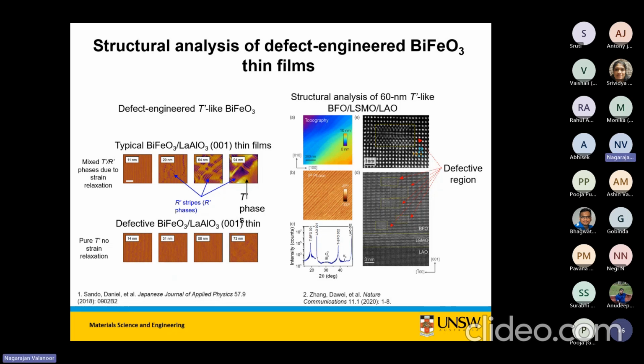So this X-ray is not very, very impressive, but if you look at those papers, you will find very nice satellite reflections, and the T phase is a really clean and beautiful interface and rocking curve and things like that. 15 minutes. Okay, I will really talk fast.